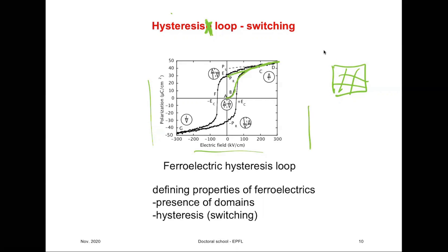By applying the field from 0 to positive and then going back, the field, if strong enough, will start reorienting domains along those crystallographic directions that are allowed by the crystal symmetry. Remember, in a tetragonal material, polarization and strain can only develop along 0, 0, 1 and perpendicular directions, under 90 degrees. They cannot develop under other directions. That's not allowed by the symmetry of a tetragonal sample.